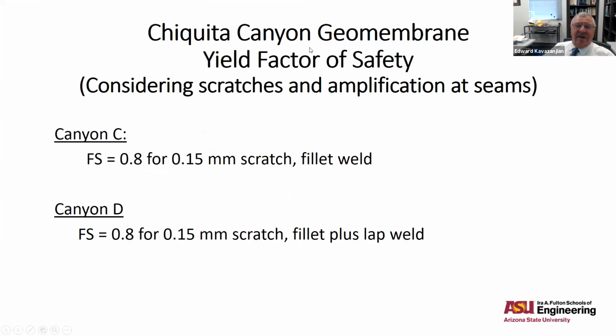So when we take those strain concentrations into effect, we take into account the reduction of the yield factor of safety, voila. We now have a factor of safety of 0.8 for a 0.15 millimeter scratch in the fillet weld in Canyon C. And we have a 0.8 factor of safety for the 0.15 millimeter scratch for the fillet plus the lap weld in Canyon D. Those are some pretty dramatic reductions, suggesting that tensile strains of 2 to 3% can send a geomembrane to yield.